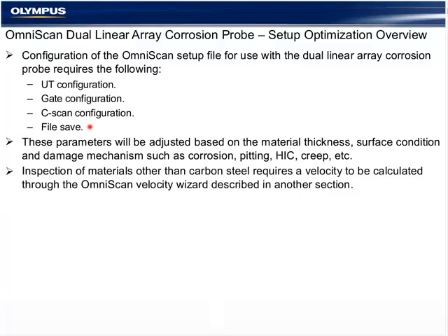These parameters will all be adjusted based on the thickness, surface condition, and then any different damage mechanism you should be looking for. But for the most part, the overwhelming majority of applications for this probe are going to be hand scanning for thickness readings and corrosion backwall monitoring. Inspection of materials other than carbon steel requires a velocity to be calculated in the wizard through the OmniScan.